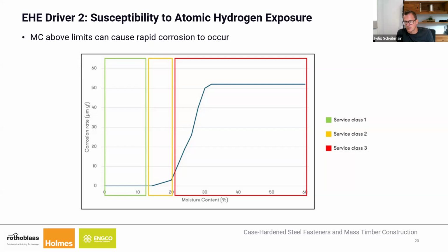And you see that it accelerates until you've got your fibre saturation point in your timber, and then it plateaus out again. But between that 20-odd% moisture content and 30% moisture content, your corrosion really does go through the roof. So it's important then to understand, okay, can I either stay out of that zone altogether by having a rock solid moisture management plan, or do I need to consider the fastener type that I'm using and maybe look at the hardness of the fasteners, or do I need to look at the coating on my fastener to ensure that I'm protecting that core, and then also looking at the install and bits and pieces to go with it.